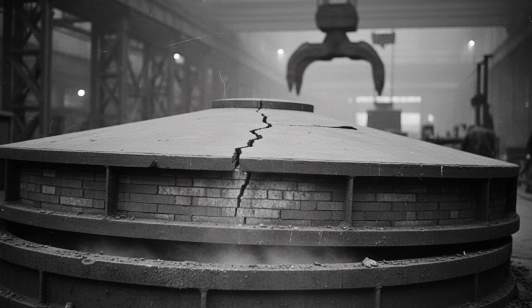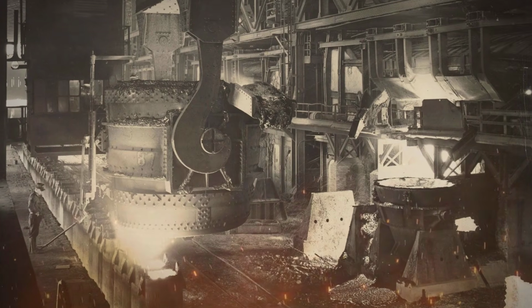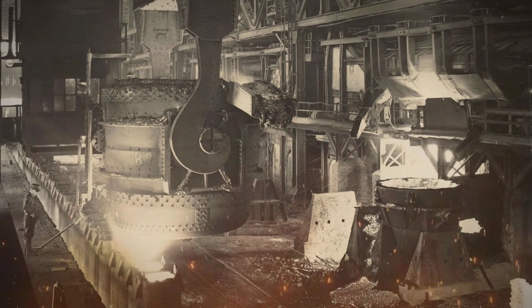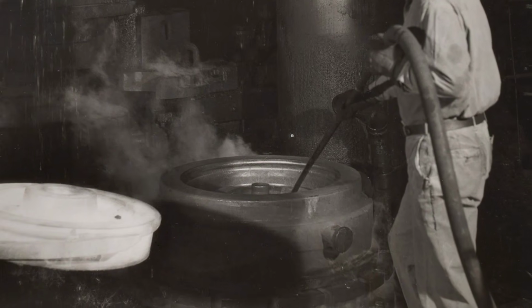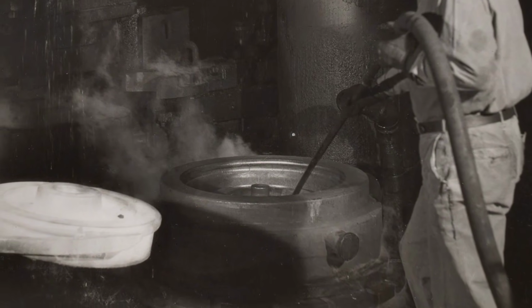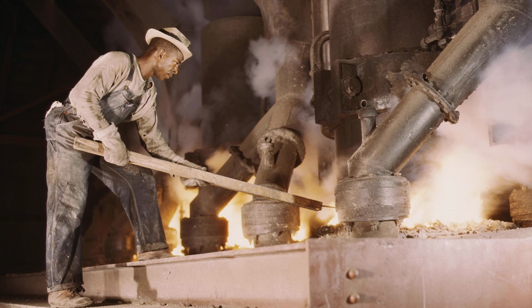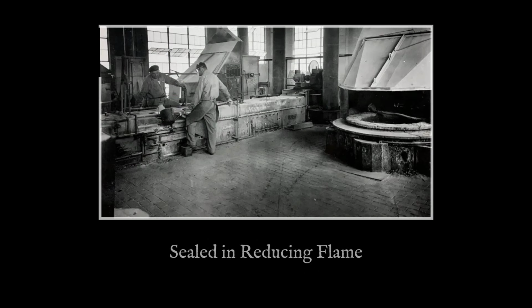A cover set down improperly could crack under thermal cycling and expose the pit edge and the floor crew to radiant heat from below. Below the cover, the pit burned continuously on producer gas fuel through burners built into the pit walls, and the atmosphere inside the cavity was a reducing gas environment at full heat around the clock.